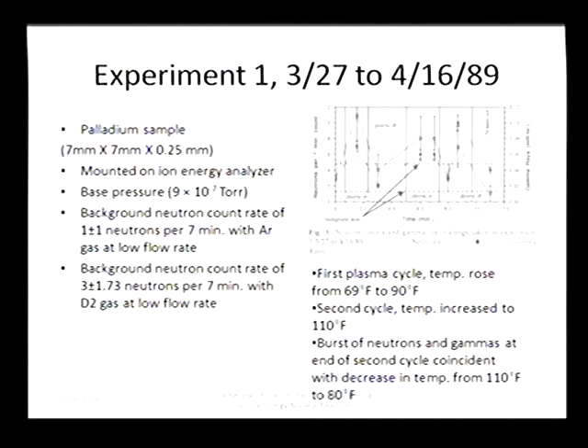We then turned on the plasma, and what we'd noticed was that basically both the neutron counter and the gamma counter went up exactly the same in time. We had a computerized system where we were able to do analysis of the data. The data went straight to the computer, so we had a real-time view of count rates of both gammas and neutrons.